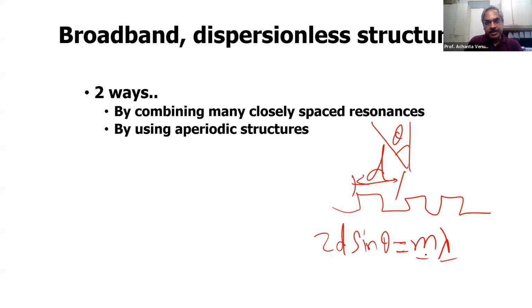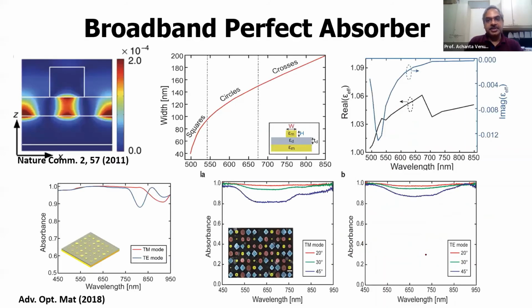But we can have broadband response structures by combining closely spaced resonances. For example, you can have different shapes. Say I want to get a metamaterial which works from 500 nanometer to 850 nanometer. Then what I can do is take square shapes of these scattering elements, covering a certain wavelength range, then circles for a different range, crosses for the other range. And then I randomly distribute them in an array to get a broadband response. So this is a perfect absorber, where we could get about 99.8% or so absorption within a 10 nanometer silicon layer.